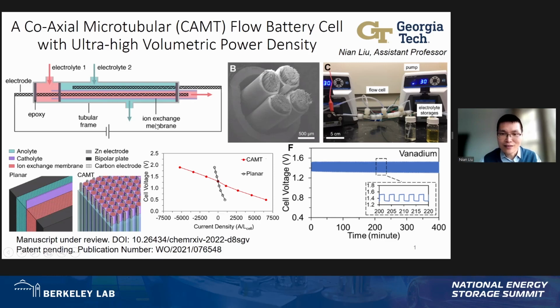And this kind of configuration, from finite element analysis, can give you a much higher current density at the same cell voltage. And we assemble the cell, and the cross-section image looks like this, and it's very small. And we have demonstrated this using the vanadium redox chemistry. And this is how our lab scale demonstration looks like.